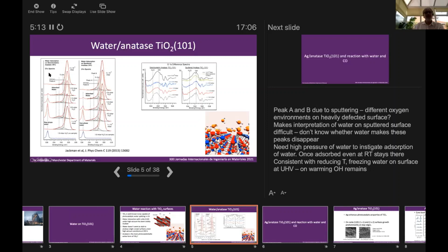So in this study, what we wanted to do was look at how much effect oxygen vacancies at the surface had on the water adsorption on this anatase surface. And could we actually get water to adsorb if we went to more realistic pressures in our system? So 6 millibar water vapor pressure here would be equivalent to about 15% relative humidity at atmospheric pressure. So we start here, this is the stoichiometric surface. So we have the 2:1 oxygen to titanium ratio.